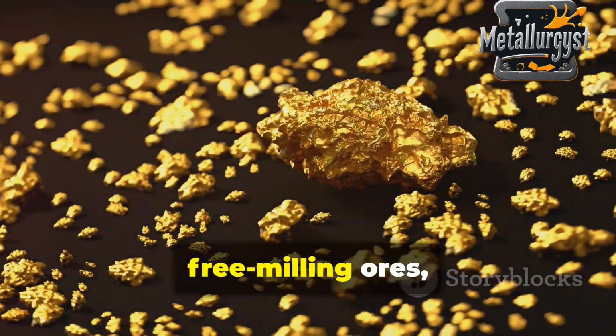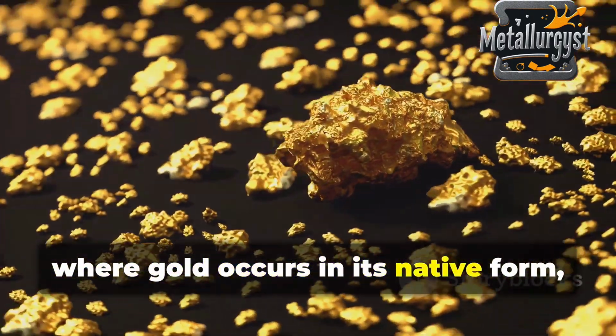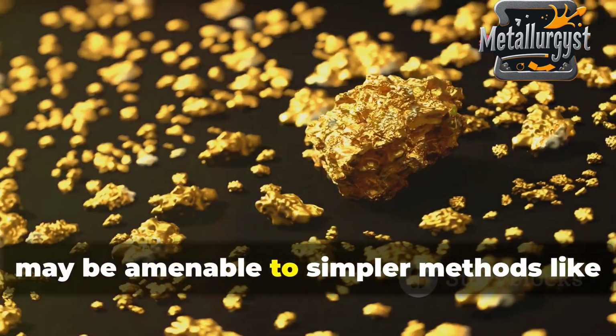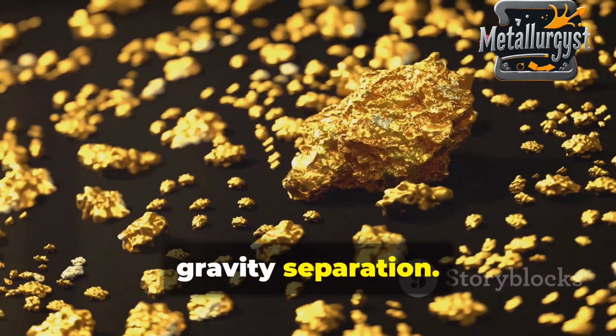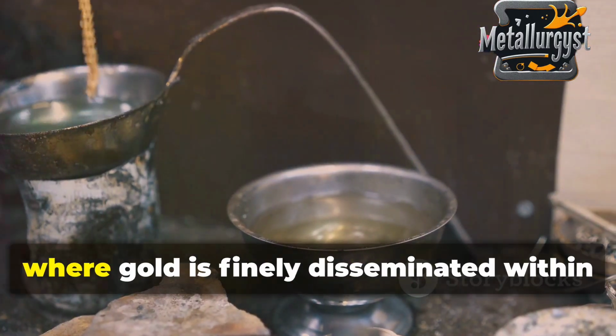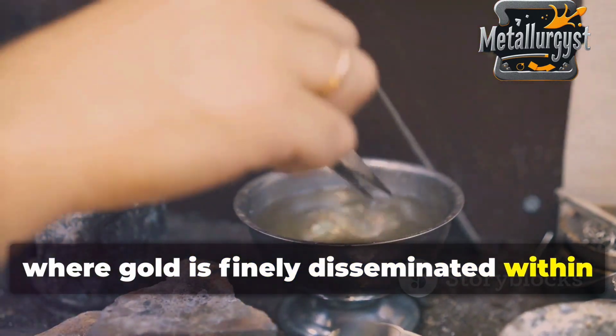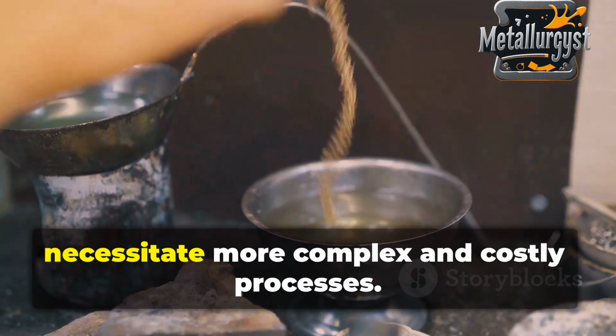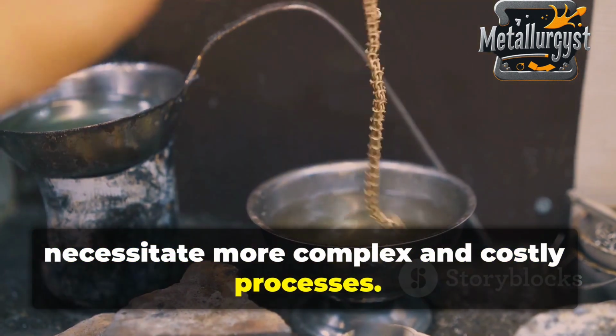For instance, free milling ores, where gold occurs in its native form, may be amenable to simpler methods like gravity separation. Conversely, refractory ores, where gold is finely disseminated within sulfide minerals, necessitate more complex and costly processes.